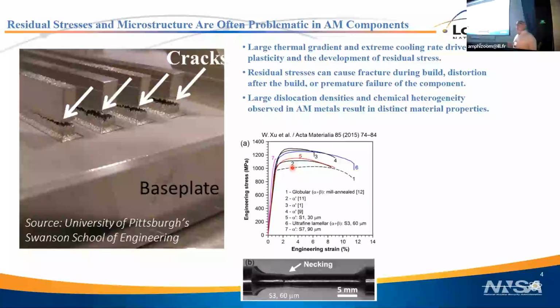Almost all of the alloys that we use were designed for casting. That means they were designed to cool down slowly. Ti6-4 is a great example. When you use additive manufacture, it cools down at 1,000,000 degrees per second, and the vanadium doesn't have time to move around where it wants to be. So you end up with a very metastable microstructure because you've frozen the vanadium into a phase it doesn't want to be in. That gives it different properties, but it also means it might not age well, because as it sits at temperature, that vanadium might move around. So additive offers some unique challenges.